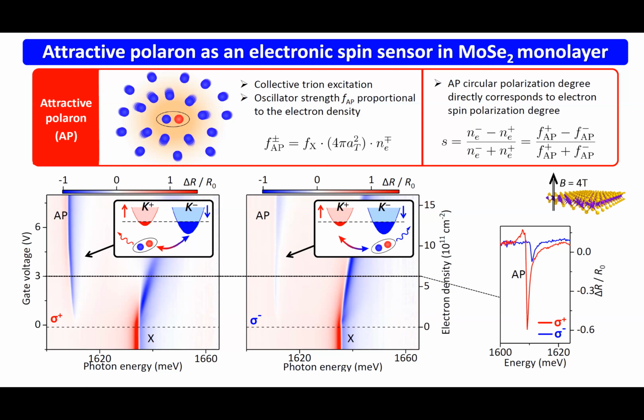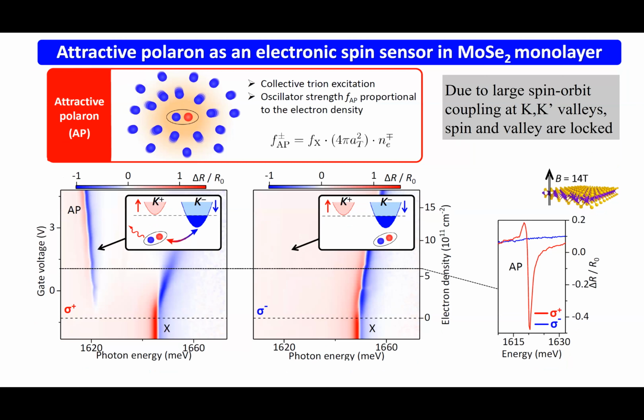There are Landau levels, but as I said, the effect of the Landau levels, what we discussed yesterday, is relatively minor. You can see these cusps. Actually, this goes up to 5 or so. This is nu equals 1, nu equals 2, etc. Whenever the electrons are in an incompressible state, their ability to broaden and shift the excitonic states is partially compromised. It's only very little, right? Because these gaps are only 2 milli electron volts, whereas the relevant energy scale in the system is the trion energy. So there is an effect, but it's a small effect that has to do with the Landau quantization.